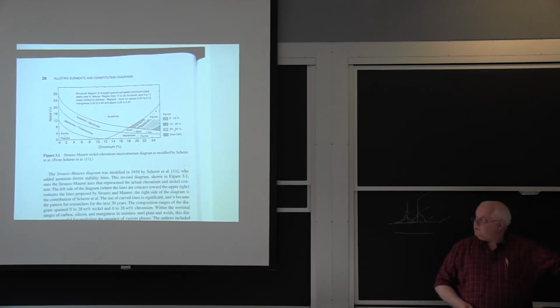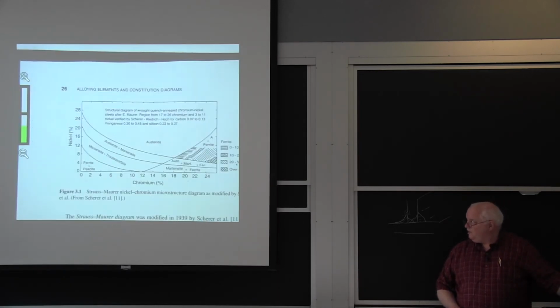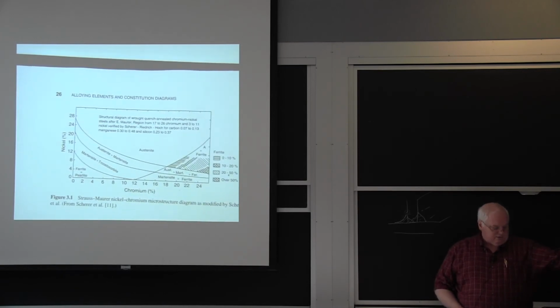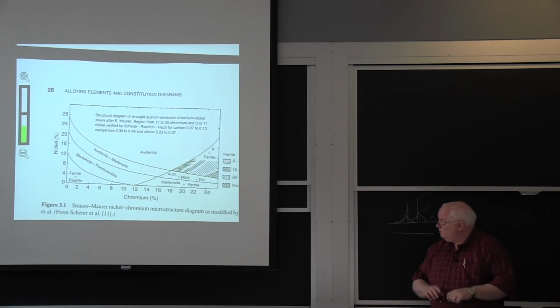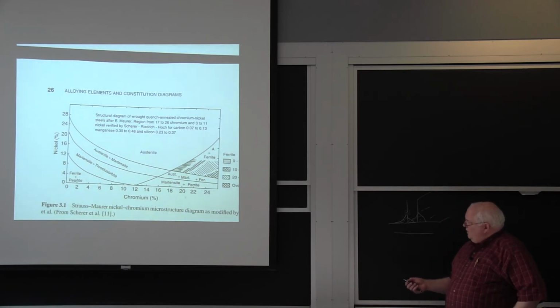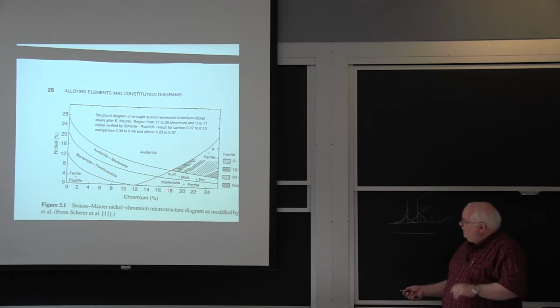Okay, if you look at the iron, chrome, nickel phase diagram, this is part of a ternary phase diagram. It's plotted not in a triangular form, which is what a pure metallurgist would do, but in a rectangular form. If you look at the nickel and chromium content, so 18-10 is right here in the austenite, okay? It costs money to put chrome and nickel in, and you can get right up here, 18-8, it's right in here, and that's your 304 stainless steel.